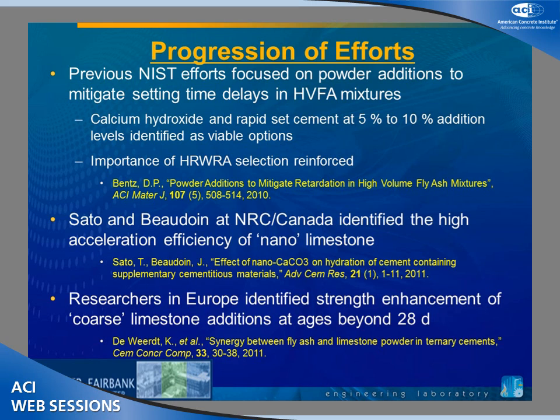We found calcium hydroxide and rapid set cement at 5 to 10% additions. They were the two most viable options for bringing the set times of a high-volume fly ash mixture back to what we saw in the control ordinary Portland cement concrete. Calcium hydroxide, I should mention, though, usually comes with about a 15% hit on your 28-day compressive strength. The rapid set cement, on the other hand, produced equivalent or higher 28-day and longer-term strengths.